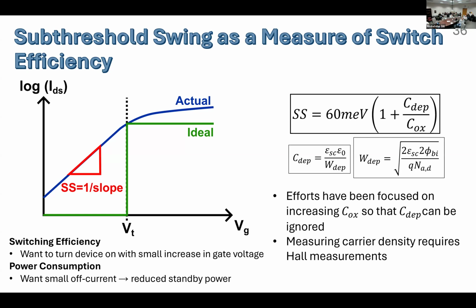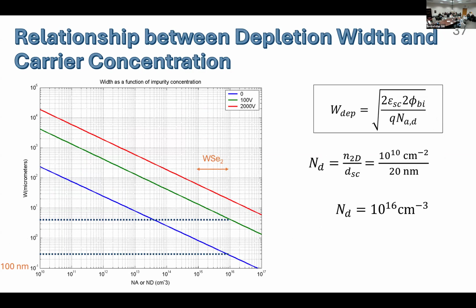And in order to obtain a value for the carrier density, we would have to do Hall measurements, which would be very time consuming. And we would have to do that for every thickness, which is not easy to do. So in order to bypass this, I decided to look at the relationship between the depletion width and the carrier density.